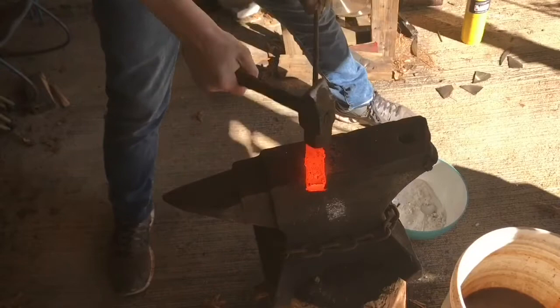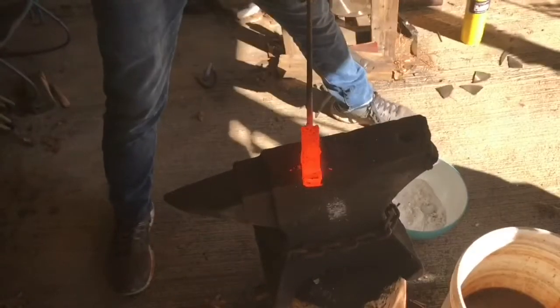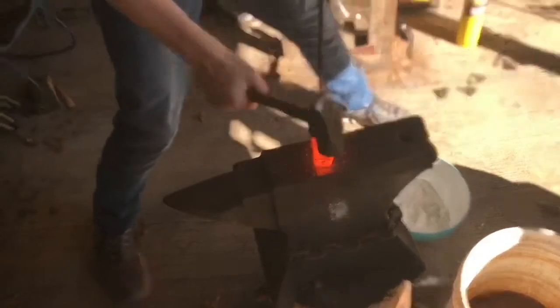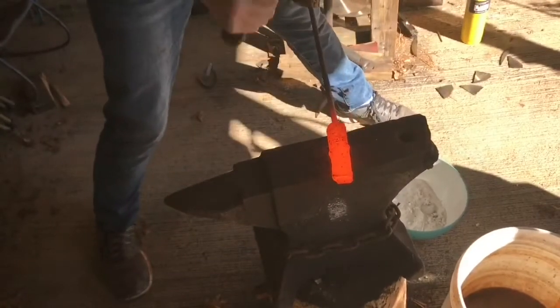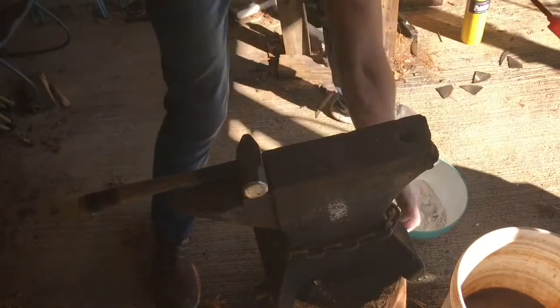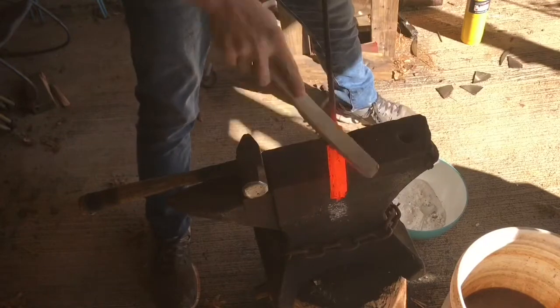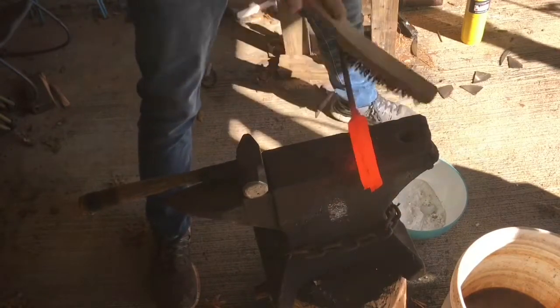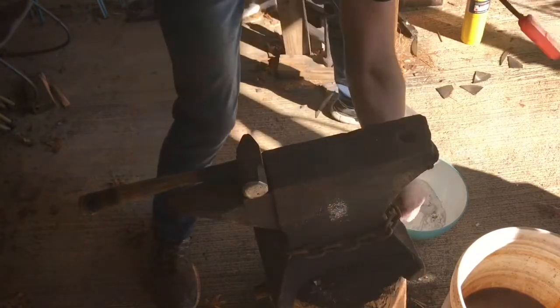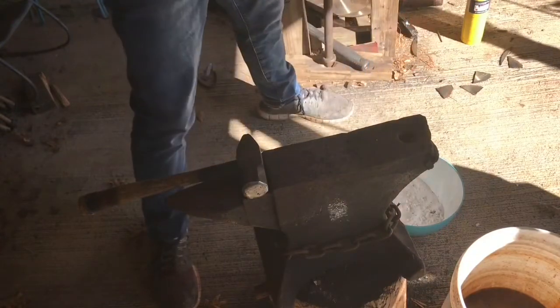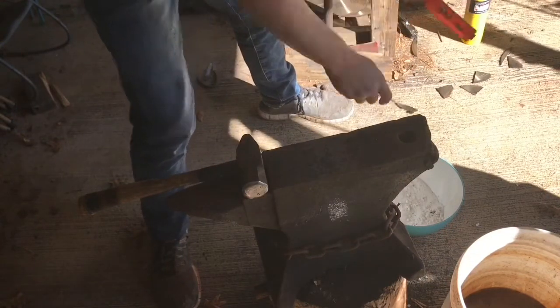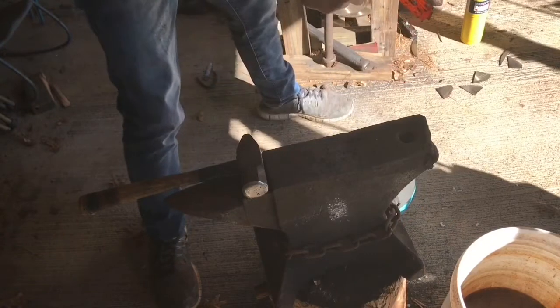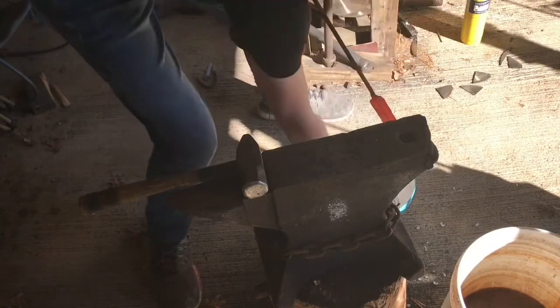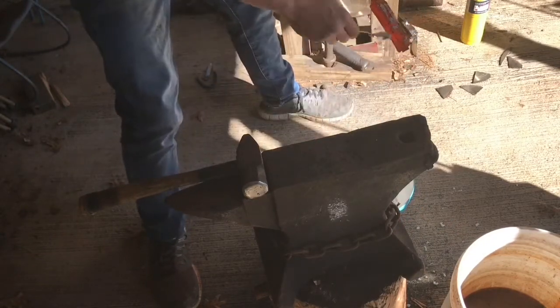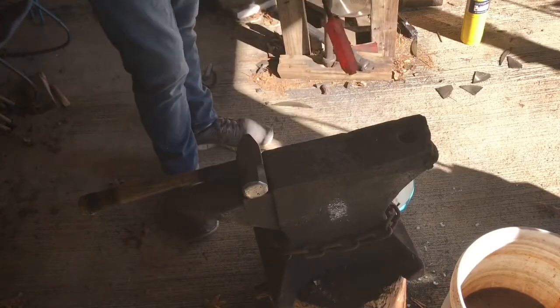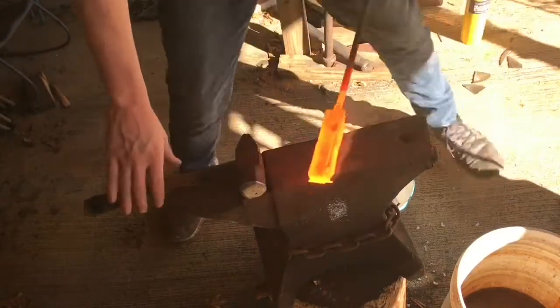You can get a little more aggressive now that the welds have started to set. You don't want to do too much though, because you risk setting the weld and then breaking the weld. So just do a little bit at a time for the first few heats. Once it's back up, then we're going to take it up to one more welding heat.